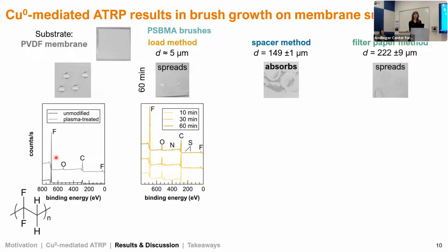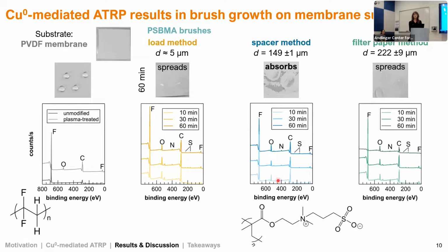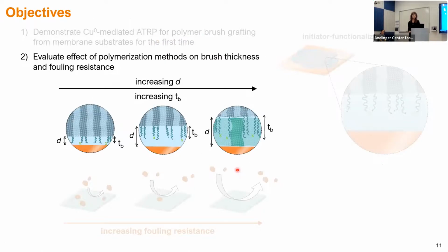After brush growth, starting again with the load method, and here we have 10, 30, and 60 minutes polymerization time, in all cases we see a higher oxygen to carbon ratio, and we also see peaks associated with nitrogen and sulfur, which tells us that our brush layer is present. And we see very similar results for both the spacer method and the filter paper method. So confirming that in all cases, with all methods, we can achieve brush growth. Okay, so that's our first objective.